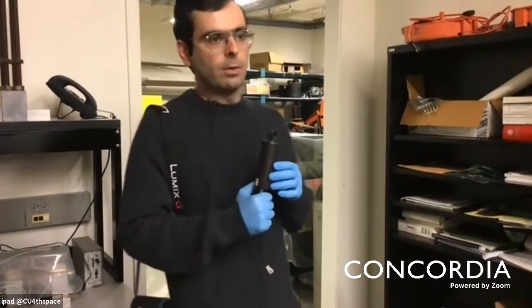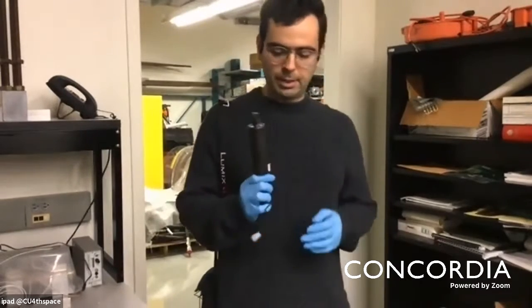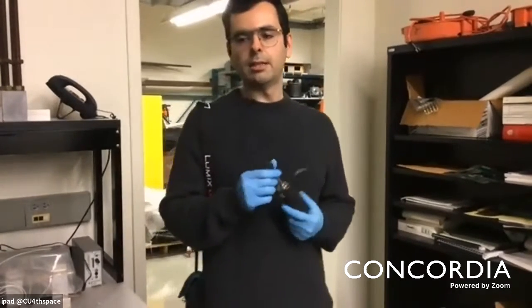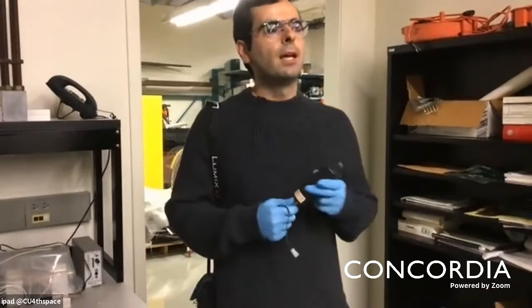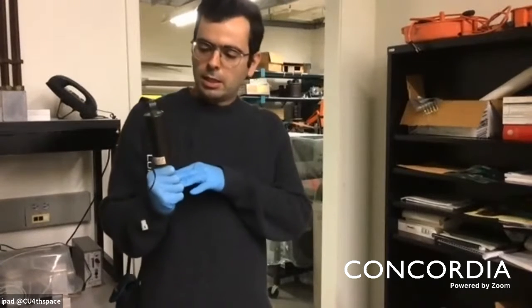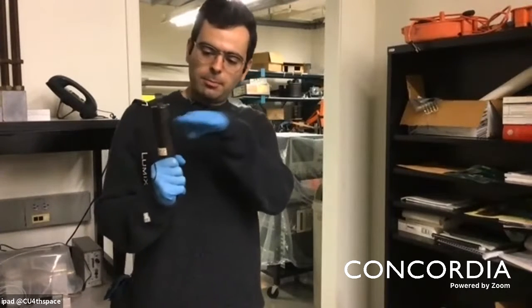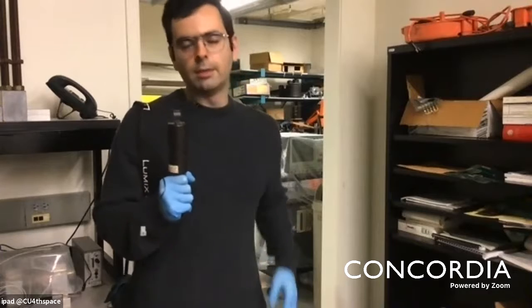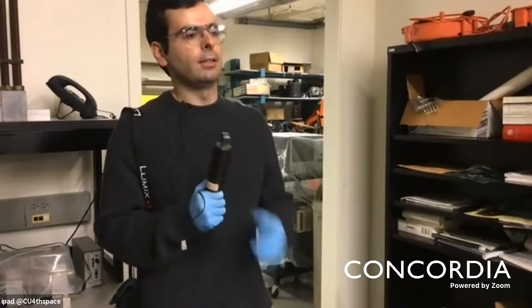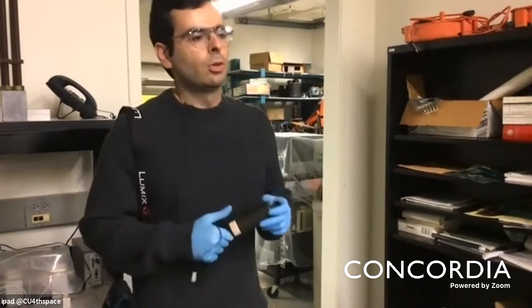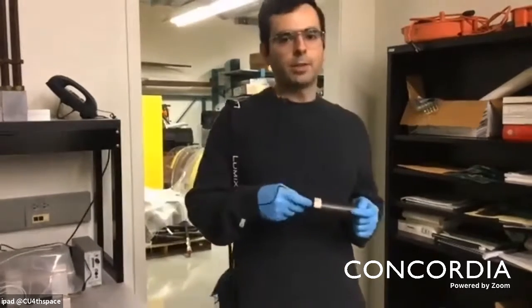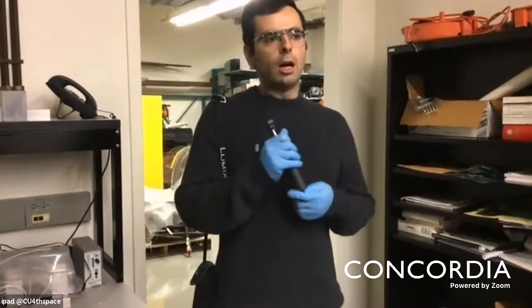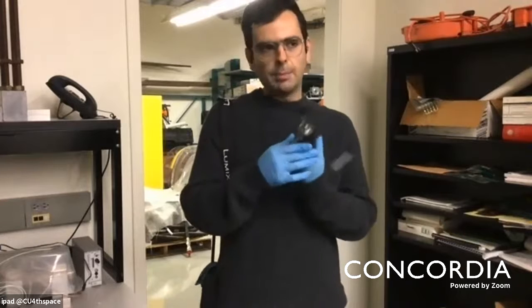They're quite temperature dependent. However, these MR dampers fabricated by Lord Corporation have lots of additives that can work with a relatively wide range of temperatures. And some researchers use fins in order to increase the heat transfer, and that allows the damper to work in very harsh conditions. So I want to answer your question. This is for MR dampers.